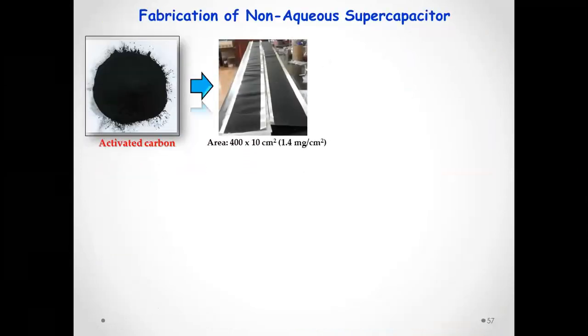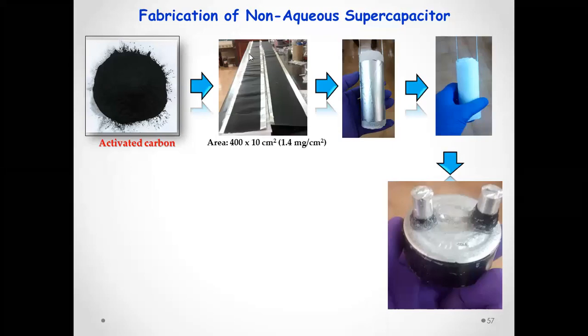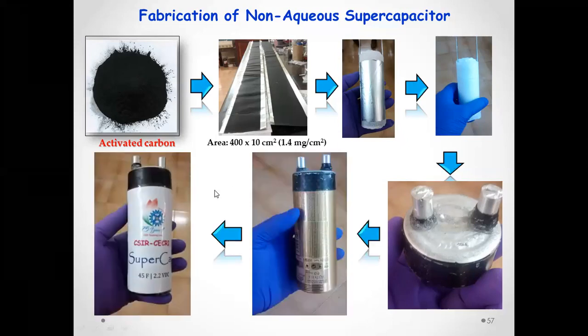This is another supercapacitor fabrication process where activated carbon is taken. We made a 4-meter tape with a 10 centimeter wide width, and we used almost 1.4 milligram per centimeter square. This is the coating thickness, and then we put it on filter paper, and these two electrodes are rolled up like this. This entire system is put into a small can, like a body spray can. Then we connected this, and we could have 45 farad. Since we use non-aqueous electrolyte, we can go up to 2.7 volt. For safety reasons, I restricted it to 2.2 volt.